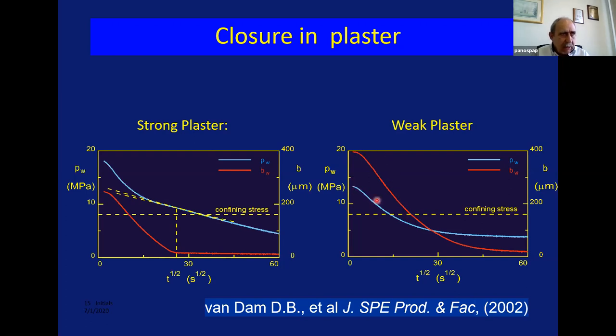the pressure drops to the value of the confining stress, which is around here, the fracture is still open, widely open. And actually, it will close the fracture here at negative net pressure, at pressures lower than the confining stress. So again, we need to be very careful with interpretation of the mini frac in weak formations.